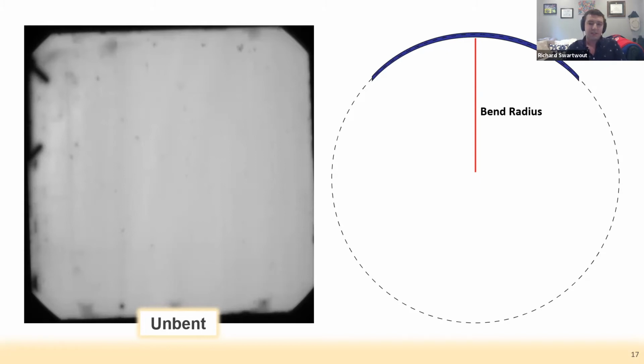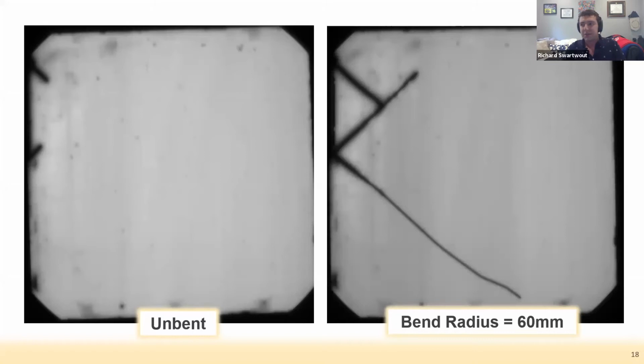So if we take this SunPower cell and bend it to a radius of about 60 millimeters, we start introducing cracking into the cell, which permanently damages it, making it non-functional. This is a fundamental limitation to silicon. It's a brittle ceramic material, and it's in a large area wafer format, so it's really hard to get around this.